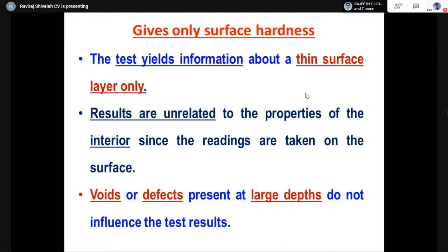And the most important information that you need to be aware of for this particular instrument is that the rebound is purely based on surface hardness, correct? In the sense that when you take a rebound, you're doing it on the surface. So if the surface is very good, obviously we get a very good number. The assumption made in this test is that whatever property or characteristic of the concrete we have at the surface, we assume that the same thing has extended inside the member. That's the most important assumption.